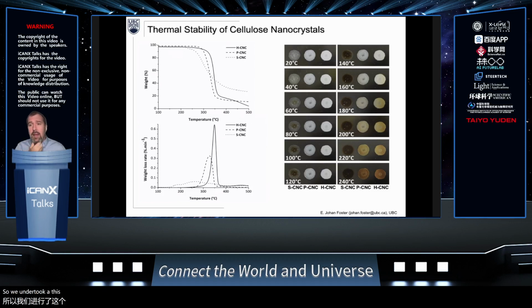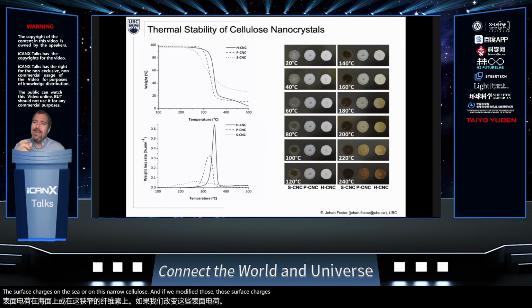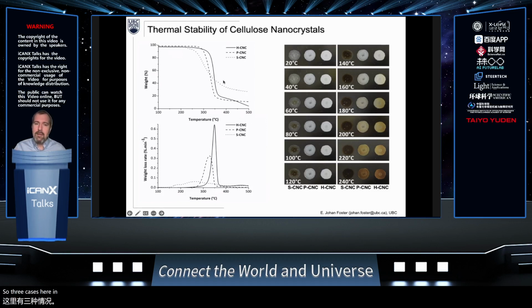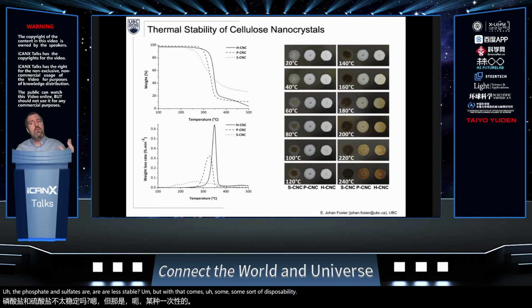So we undertook this is a paper we published maybe about 5 years ago now, where we looked at the surface charges on this nanocellulose, and if we modified those surface charges, we can change the dispersibility, so the ability of this to be dispersed into a solvent, and with that comes a change in thermal stability. Okay. So 3 cases here in the top left. H means that there's only a hydrogen, those hydroxyl groups are just hydrogens. The P means they're phosphate groups, and the S means they're sulfate groups. So you can see that the H, the solid line, is the most thermally stable. The phosphate and the sulfates are less stable, but with that comes some sort of dispersibility. So you need to be able to balance that, because one key part about having this fantastic cellulose nanorods is their ability to be put into other materials.